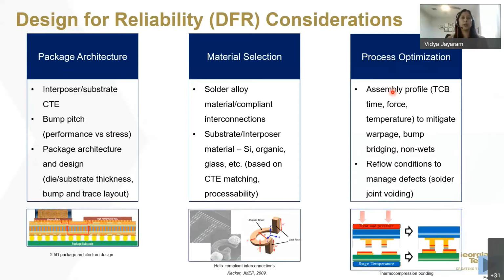So going into a little more detail about the design for reliability considerations. You have three main components to it. You have the package architecture, where you would consider what kind of overall architecture you want to pick. Is it going to be a 2D or a 3D package? Is it going to be wafer level fan out? Different kinds of architectures that you want to pick. In addition to that, it would also include geometry: what your bump pitch is, what your die thickness is, what your bump and trace layout would look like, or what CTE you want to pick for your substrate based on what CTE mismatch you would expect. So it's a game of balancing performance versus stress.